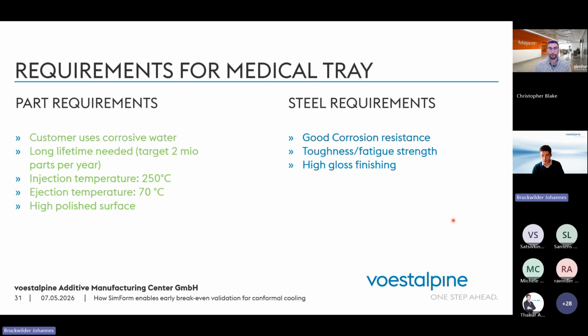Coming back to the medical tray, the part requirements are that the customer uses corrosive water. So we definitely need to go for a corrosion-resistant steel. There's a long lifetime needed. As I said, the target is 2 million parts per year, and it should last longer than 2 million shots. The injection temperature is 250 degrees, the ejection temperature 70 degrees, and we need a highly polished surface. That's the part requirements, and translated into steel requirements, we need good corrosion resistance. Regarding the cyclic fatigue behavior, we need a tough and fatigue-resistant material. We need a high gloss finish. There is no glass fiber content in the plastic, but still it needs sufficient hardness so that you are not creating any wear.